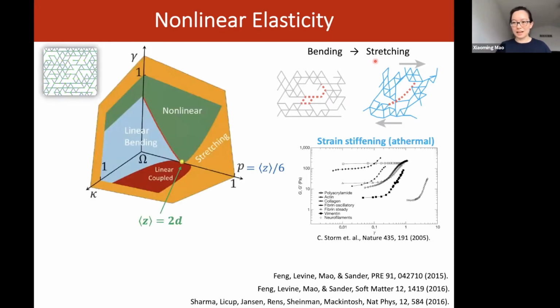By studying various lattice models, we arrived at this three-dimensional phase diagram for the nonlinear elasticity of fiber networks, where this plane is the linear elasticity phase diagram that you have seen on the previous slide, and this axis is the nonlinear strain. So as you start from a linear bending regime, which applies to most fiber network materials, and go up, you prepare force chains, and the network has a transition from floppy to rigid elasticity, and eventually it crosses over to the stretching dominated regime, and the elastic modulus can change a lot from this crossover. This explains the strain stiffening for some of these polymeric materials in an athermal picture, and some other materials, depending on the type of fibers, could also have strain stiffening by stretching out thermal fluctuations. So there are different mechanisms that can give you strain stiffening.